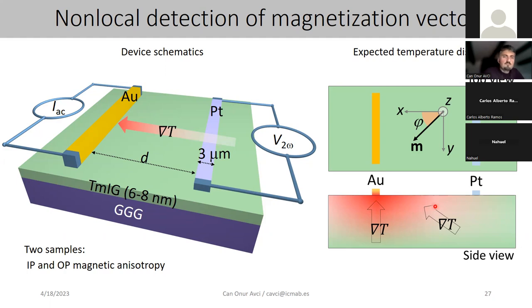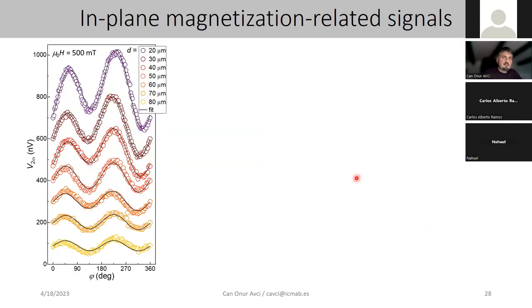First, I'm showing you the second harmonic signals, which are basically related to the thermal gradient in the platinum channel, by rotating the sample in a fixed magnetic field of 500 millitesla. So this is the in-plane rotation. As you can see, there's a complex sinusoidal behavior, which we did not understand in the beginning.